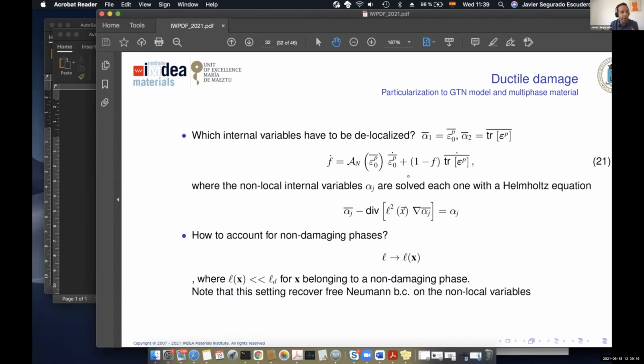Well, I don't have it here, but it is proved by taking a volume over two faces, making the integral and imposing the continuity of the fields, you end up with a relation in the interface between the two faces. This relation tells you that if you want a free Neumann condition, so that the damaging phase has an evolution of the internal variable whose gradient multiplied by the normal is equal to 0, it can be done if on the other side you have a characteristic length that is much smaller. I'm not putting any detail here, but this is formally proved.